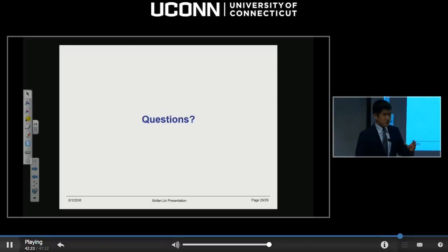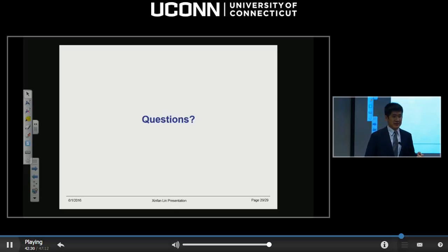I didn't do that work myself. We have a couple of people working on that, and I'm responsible for my part. I think what he did was try to fit and align the peaks. We have a line profile consisting of peaks, and he compared two images. There will be a shift because of the expansion, so he tried to fit and align those peaks back together. In this way he figured out the expansion and corrected for it.